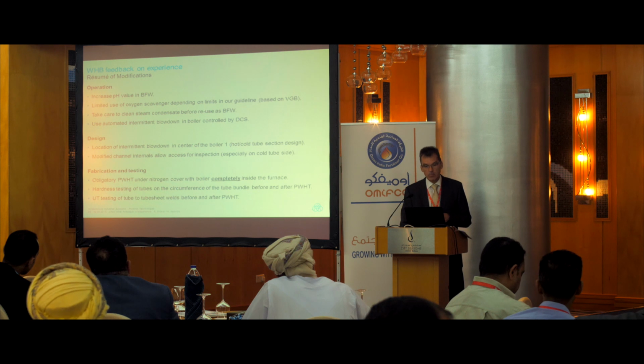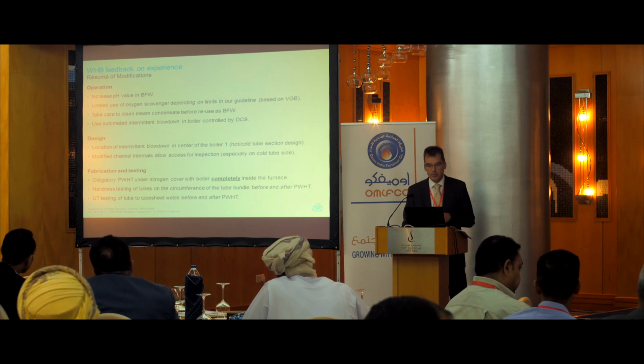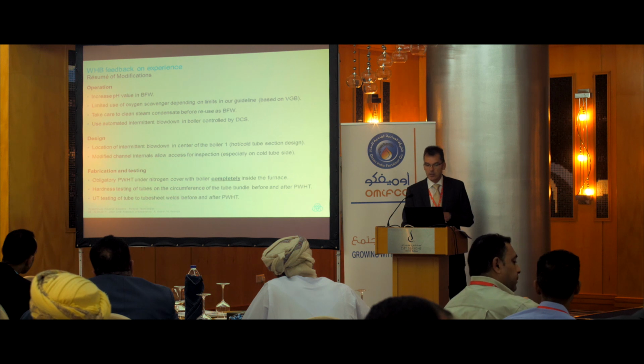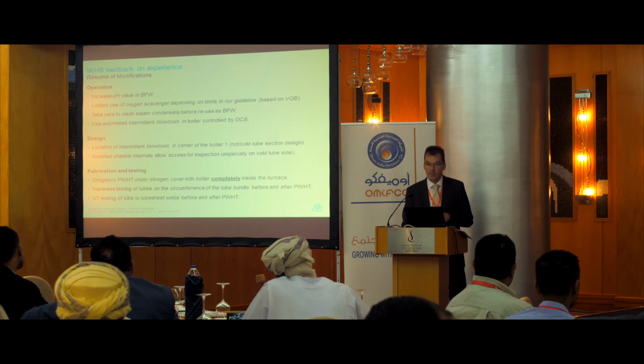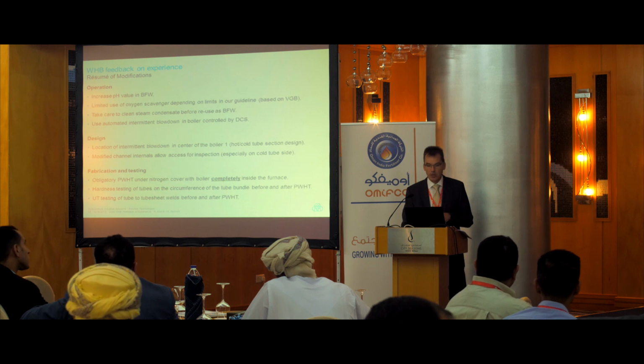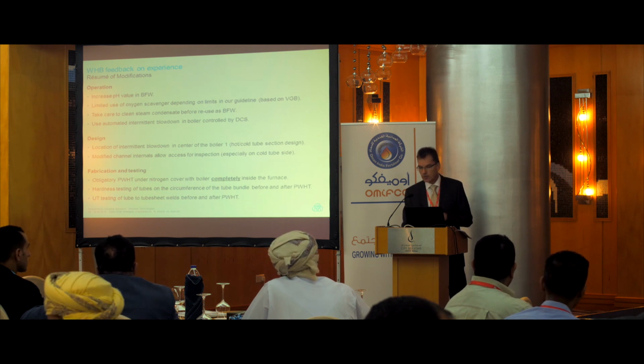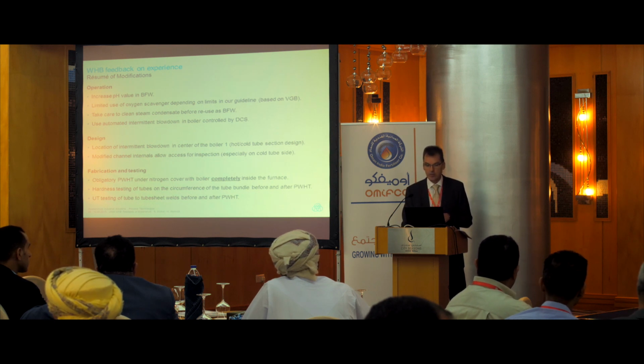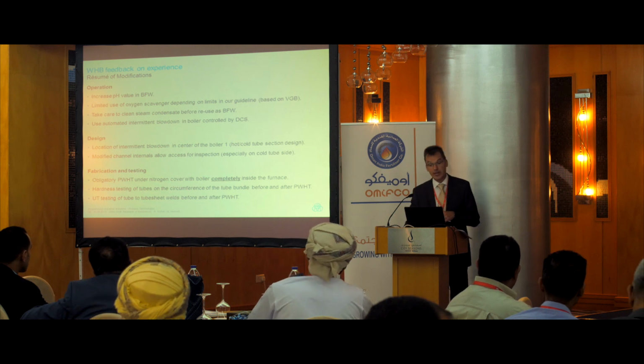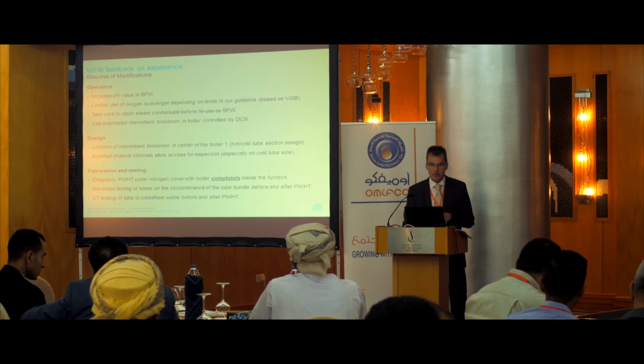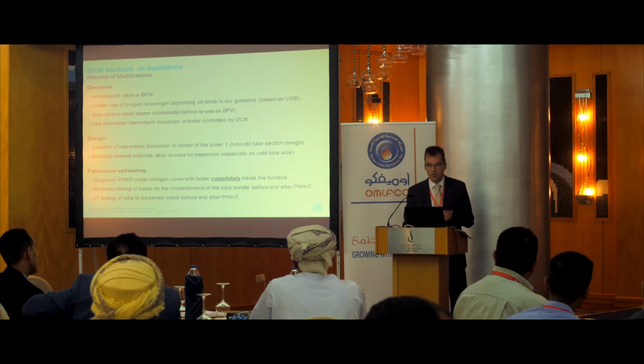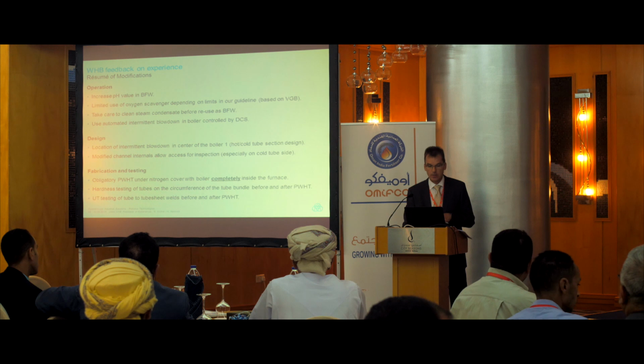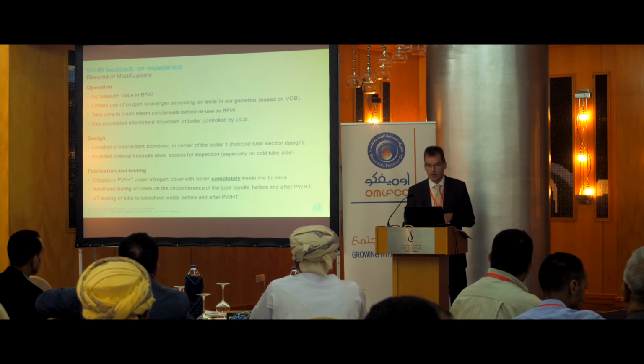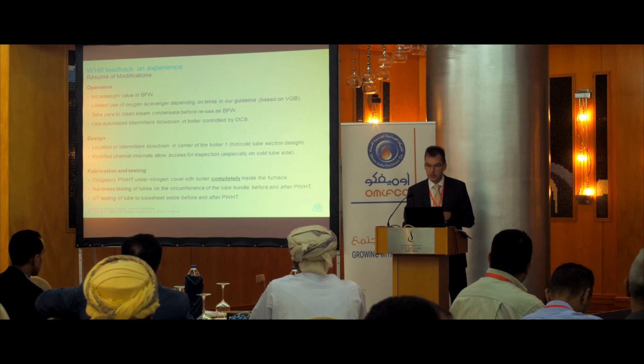What did we do with design? You remember we changed the hot-cold sections of the tube sheet, so we have an intermediate blowdown in the center of boiler number 1 now. And we have modified the channel internals so we can better check during turnarounds the status of the waste heat boiler with eddy current tests. What is important for fabrication testing? We said before obligatory post-weld heat treatment under nitrogen cover with the boiler completely inside the furnace. Hardness tests on tubes are mandatory, and ultrasonic tests of tube-to-tube sheet welds before the post-weld heat treatment are also mandatory.